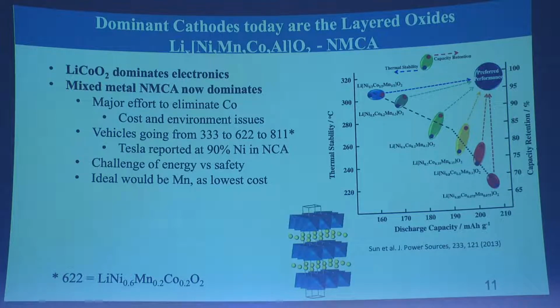So today in most batteries, EVs, grid storage, we've gone from what we call 333. This means 33% nickel, 33% manganese, 33% cobalt, up to 80% nickel, 10% manganese, and 10% cobalt. That has cut the cost of these cathodes down by more than 50%, because almost all the cost is in the cobalt. So we've done that. Tesla uses what they call NCA, which is nickel, cobalt, and aluminum, and they're now up to 90% nickel in their cells.